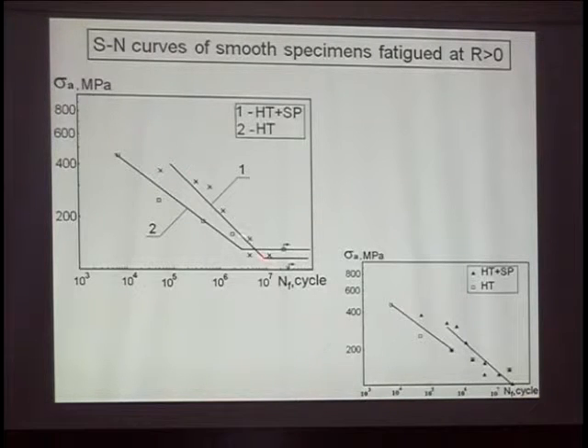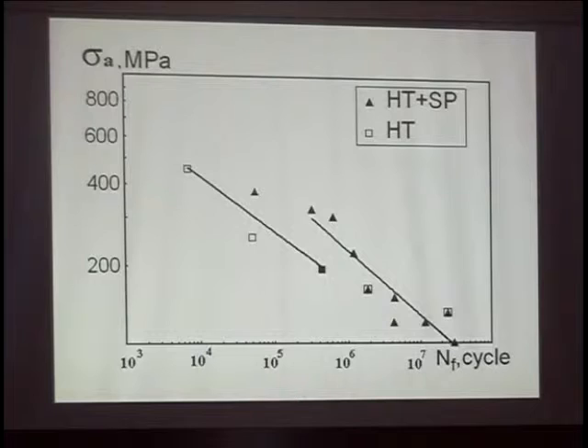The same. This is the fatigue curve that has been used to estimate the fatigue limit, but in reality these test results show us that there is subsurface cracking. So it's not the same fatigue curve. There exist two fatigue curves, and that's why the results of fatigue tests should now be differentiated, in my opinion, because if we think about fatigue limit, we should not stop our test. If we stop our test, we should open, if possible, the inside of the material to look for cracking if it exists. If not, we should think that maybe the results of the investigation should be used for constructing one kinetic curve, maybe another one because of subsurface material cracking.